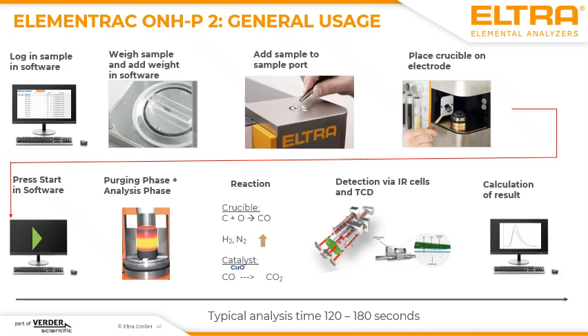The correct analysis of powder for ONH could be critical at different stages of the analysis process. In contrast to CS, already the loading of the sample could be a critical thing, because the method which is used for loading determines the kind of power you apply to the sample. When you have, for example, a refractory-based sample, whereas you usually analyze steel, you cannot use a steel method because the applied power is too low. Weighing of the sample is also a critical thing because some titanium-based samples, for example, can only be applied with a reduced sample weight of approximately 100 milligram.